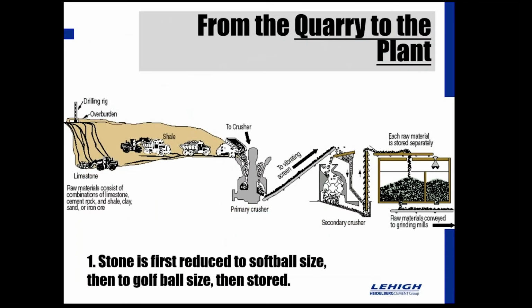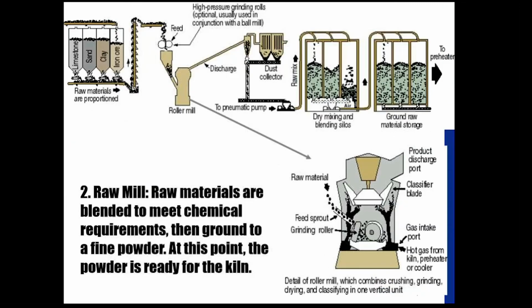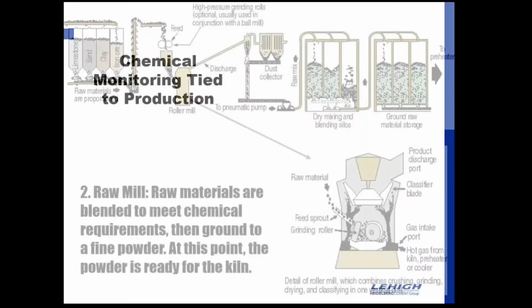And so when we take that rock from the quarry to the plant, we first reduce it to kind of softball size, then down to golf ball size, and then it's brought to the plant where it's stored. And then once we have it at the plant in stored condition, we take limestone and a sand to give us the silica, something to give us our alumina source, and then an iron source. We take those four things and blend those. And they're ground, and we want to make sure at that point that we start to really control the chemistry. They're ground specifically to a fine powder, and at that point, that material is ready to go into the kiln.